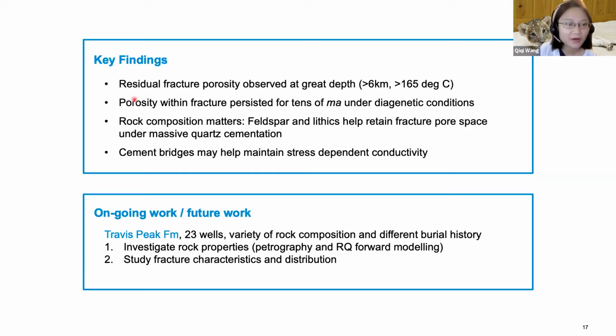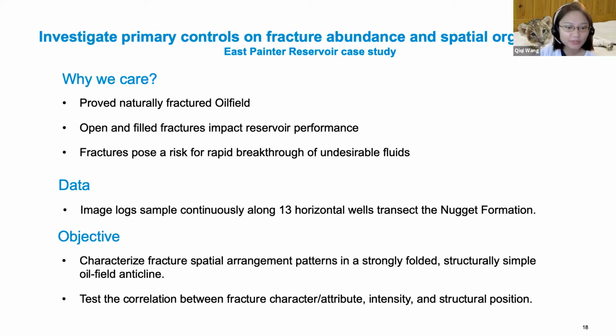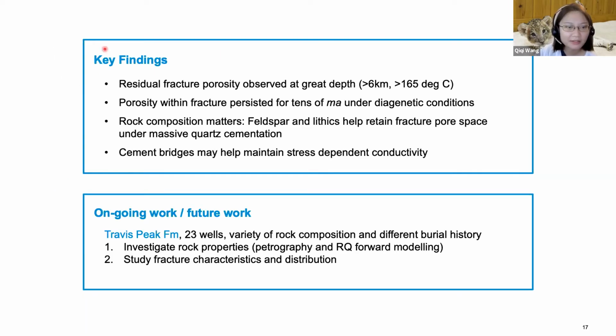And so the first part, the key findings. Yes, before I get into this reservoir scale fracture characterization, the key finding of the first part of my talk: we see residual fracture porosity observed at great depths, deeper than 6 kilometers, above around 165 degrees C under diagenetic conditions. We see residual fracture porosity, and the porosity persisted for tens of millions of years under diagenetic conditions. Feldspar and lithics can help retain fracture pore space, and cement bridges may help maintain stress-dependent conductivity.